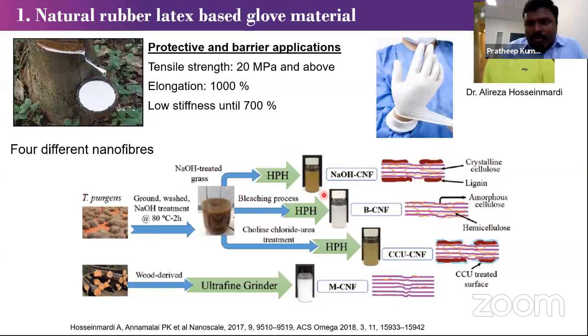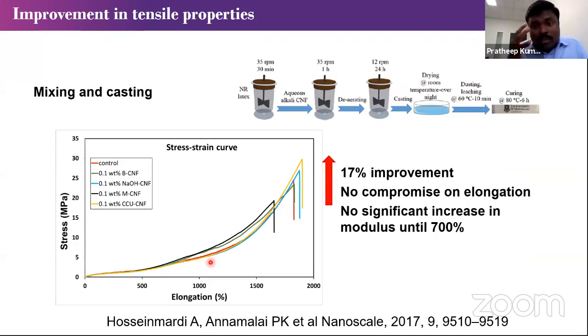So we explored different types of nanocellulose: bleached, transparent nanocellulose, and lignin-containing or hemicellulose-containing nanocellulose. We also treated with a bit of surface chemistry using choline chloride and urea, so we can get some different surface chemistry. We also compared with nanofiber based on wood. We made these different materials and could achieve really good improvement with a bit of surface modification with choline chloride and not removing lignin. The blue one is the unbleached nanofiber. So we could increase the strength. You can see that in the tensile curve, where there is an increase in the tensile strength.